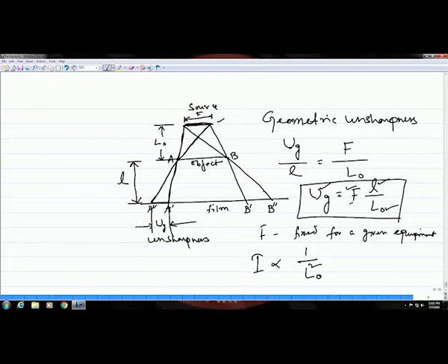Okay. So, that is why it is also difficult to change this distance between the source and the object. So, that leaves us with this distance, the distance between the object and the film, to change it and minimize it, to minimize the unsharpness. Okay. So, that means the distance between the film and the object should be minimum, and it will be best to keep the object and the film in intimate contact.